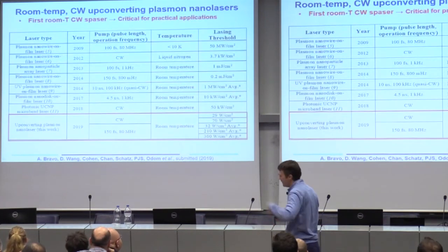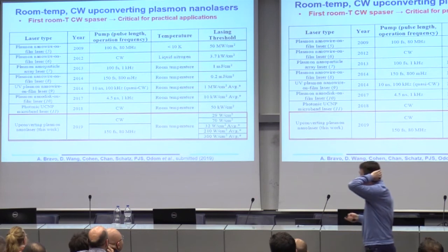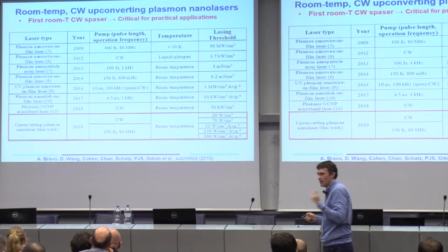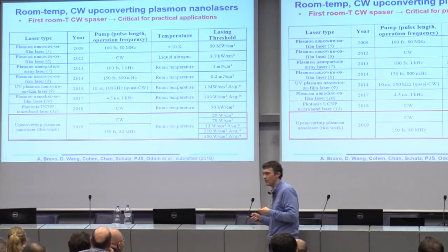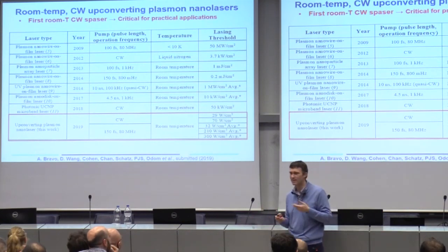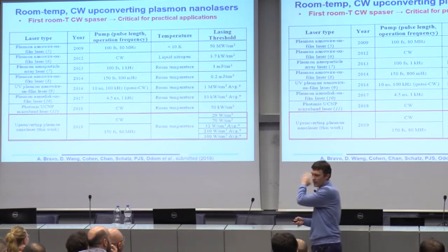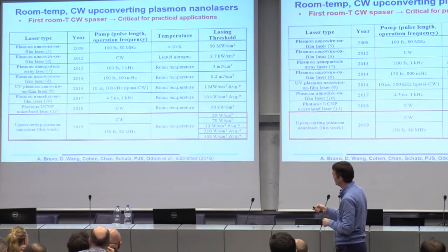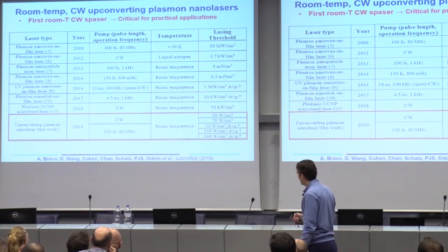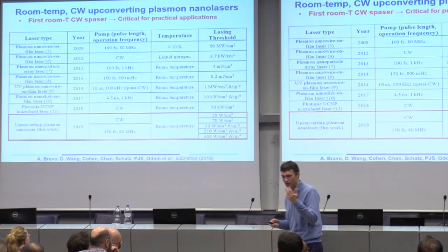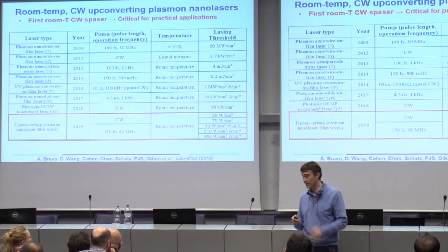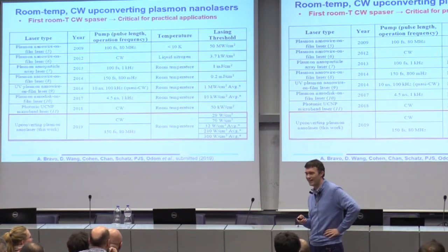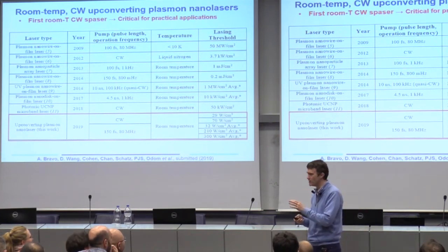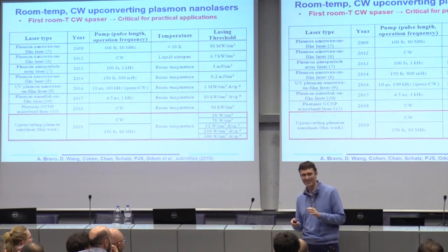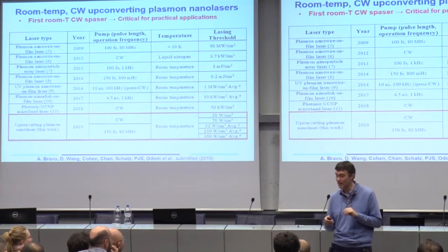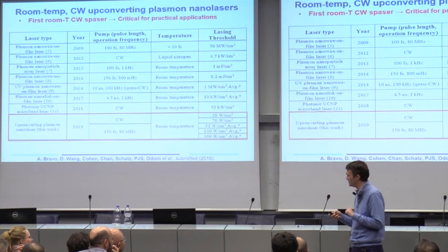All right. Anyway, I'll finish with a comparison. People have made plasmonic lasers before. People have made upconverting lasers before. No one has made a CW room temperature plasmonic laser until now, and that's what we have in our material. And our lasing thresholds are well below what anyone has seen before. Again, I'll be honest, I can't explain it fully. I can give you lots of hand-wavy reasons for why it should be lower, and just as many for why it shouldn't work. So we think there might be other things going on, some kind of superradiance or something else happening here.